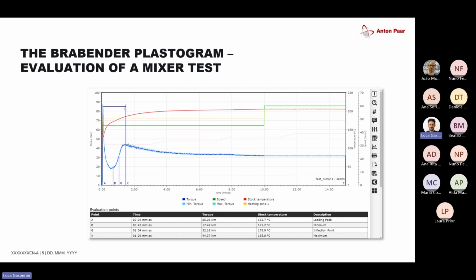So what happens during the test is, after you fill in the PVC, you get a short peak, a feeding peak, then the additives start to melt, which is shown in a very strong drop in the torque level. And then once these particles fuse together and the grain boundaries come together to form this three-dimensional network, the torque starts to rise again until it reaches a maximum, and the network somewhat stabilizes in the end, and you get a continuous process. Usually you would want to have the complete fusion process within the extruder.